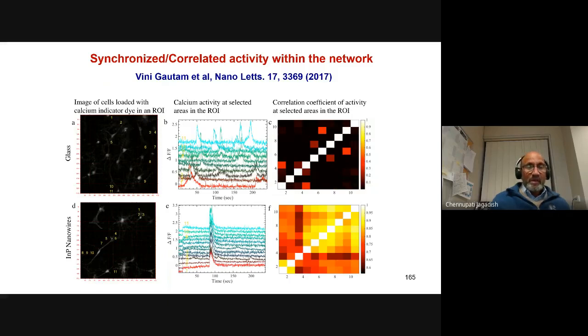the neurons. But when we grow these neurons on indium phosphide substrates, you see the change in fluorescence as a function of time, and they're all firing at the same time, indicating that some sort of synchronized and correlated activity is taking place, and the correlation coefficient looks excellent from that point of view.